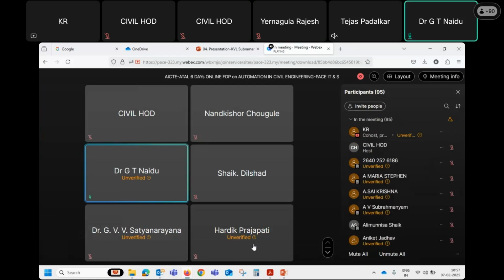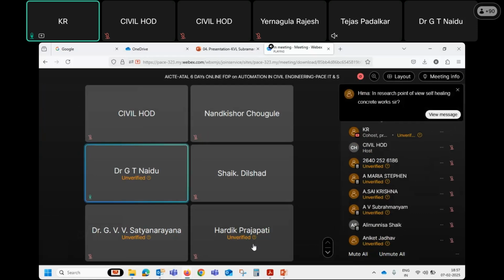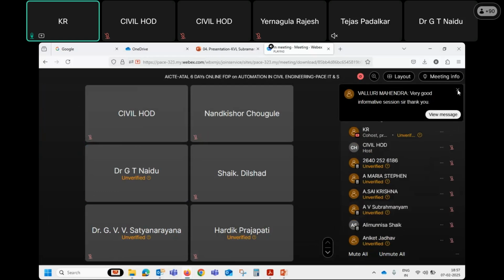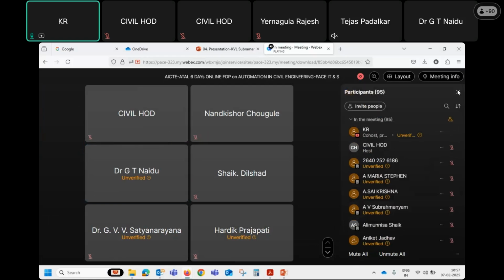We used to top up this curing, but now the rate of construction has become very fast. Nobody is keeping shuttering or formwork for 20, 25 days. They have brought it down to one week, 10 days, or even between 10 to 15 days. The construction industry is working so fast. For that reason, they now adopt higher grades of concrete and more material consumption. If the structure is designed for M30 grade, they take one grade higher, like M35, to compensate for this risk.